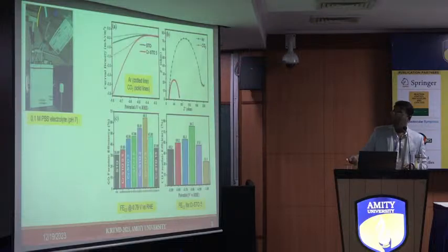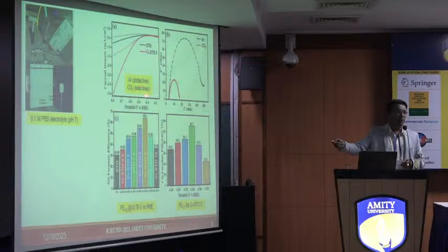Now, if you come to the electrochemical setup, what we have is an electrochemical cell made up of Teflon. It's a two-chambered cell. On one side you have the water and the anode. On the other side you have the carbon dioxide and the cathode, which are separated by the proton exchange membrane, called the Nafion membrane. When you record the linear sweep voltammetric curves, these are the curves. The dotted lines are for argon. The bold lines are for carbon dioxide. You see there is a change in the current. There is an increase in the current when we purge the carbon dioxide, right?